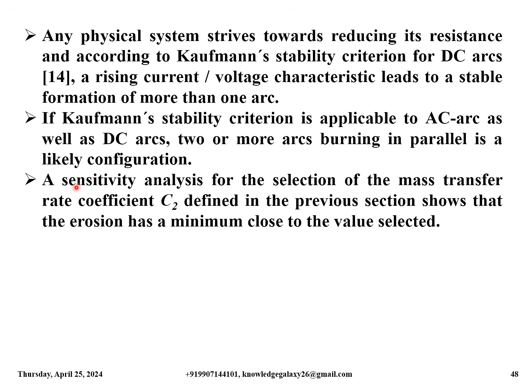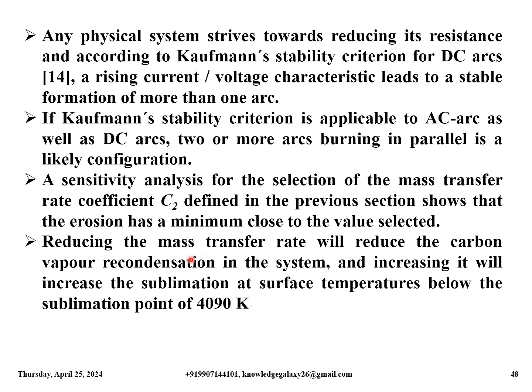A sensitivity analysis for the selection of the mass transfer rate coefficient C2 defined in the previous section shows that the erosion has a minimum close to the value selected. Reducing the mass transfer rate will reduce the carbon vapor recondensation in the system, and increasing it will increase the sublimation at surface temperatures below the sublimation point of 4090 Kelvin.